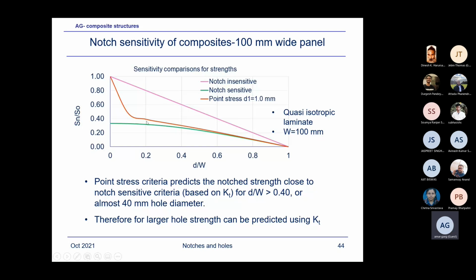So from this graph, what you are seeing here is that when the hole size is smaller, the realistic estimate of the strength is predicted by this line, which is the point stress criteria. But as the hole size gets larger, suppose this is a 100 millimeter panel, so what you are seeing here, d by w, that means the diameter is 40 millimeter. For say a 40 millimeter hole, the prediction using the point stress criteria and the prediction using the notch sensitive criteria, 1 upon kT, merge together.